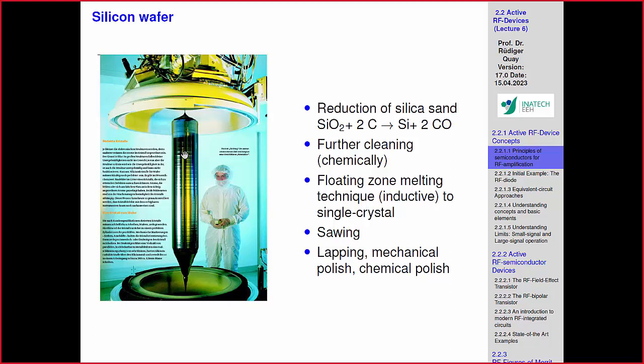You're essentially heating a crystal, and by diffusion you drive out all the dirty stuff in the crystal. Anything which is still in there is, by inductive heating, taken down, and it actually comes to this end. The reason why this happens is a concentration gradient. You heat, and there's a gravitational aspect, but there's also a diffusion aspect because you drive with a temperature distribution. You take the unclean part out, and you also heal the crystal so that you effectively get an atomically clean surface. But this is only in the crystal.